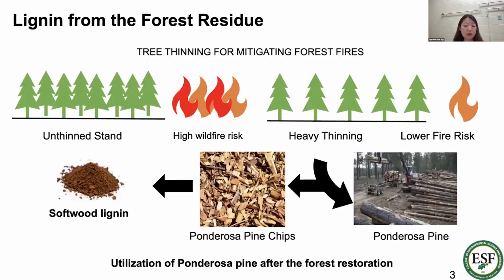Then how can we get this abundant biomass feedstock for lignin? In the US, the USDA conducts forest thinning to prevent large-scale wildfires. Ponderosa pine is often targeted in these operations, and these activities generate significant wood residues, which are often discarded or burned. Rather than treating this material as waste, we propose using these residues as a renewable feedstock. By extracting lignin from these ponderosa pine residues, we can convert these lignin bioproducts into value-added materials for sustainable polymer production.